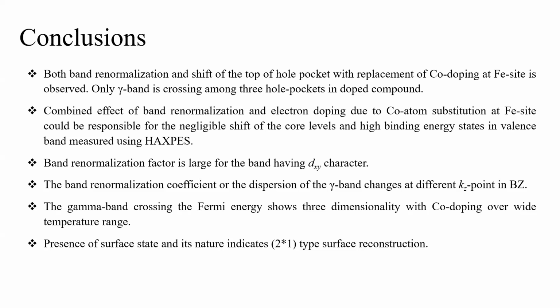Apart from that, I have one question about your photoelectron spectroscopy. If you do the gap measurement, what is the Dynes parameter value in your case? I think you are talking about the gamma in that equation. In your case you are doing finite temperature measurement and you are using photons, so there is obviously non-equilibrium heating also. If you do the low temperature measurement, what is the gamma value? Can your BCS model not fit the density of states evaluation?